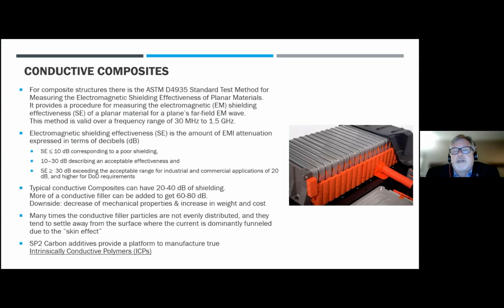We'll show some test data a little later, specifically with our product, but in general, if you have a shielding effectiveness that's less than 10 decibels, that's not appropriate shielding. If it's in the 10 to 30 decibel range, then it's starting to become more effective. And typically you want to be above that 30 decibel range to have acceptable performance in most industrial and commercial applications. Typical conductive composites have about 20 to 40 decibels shielding. But with a more conductive filler, you can get it up to 60 to 80 decibels.